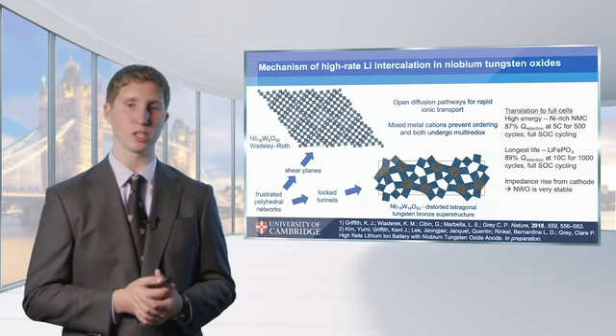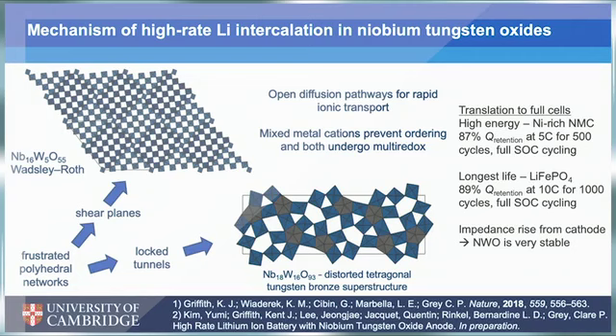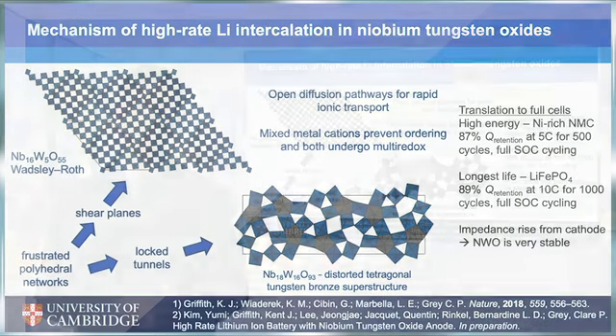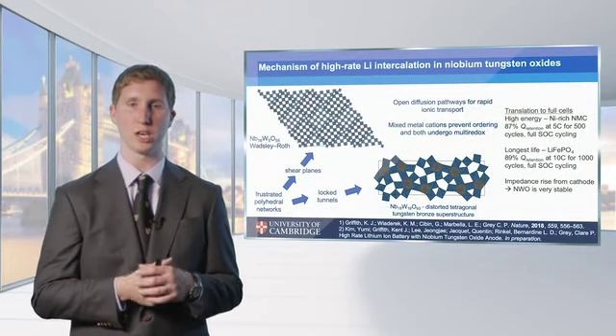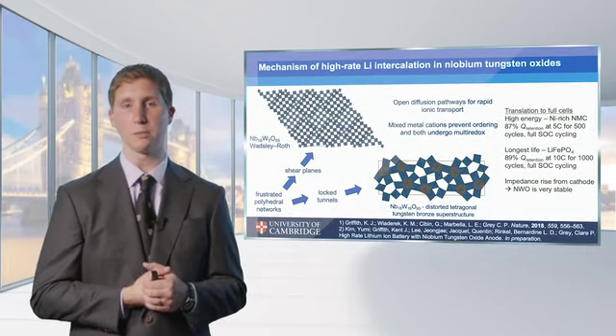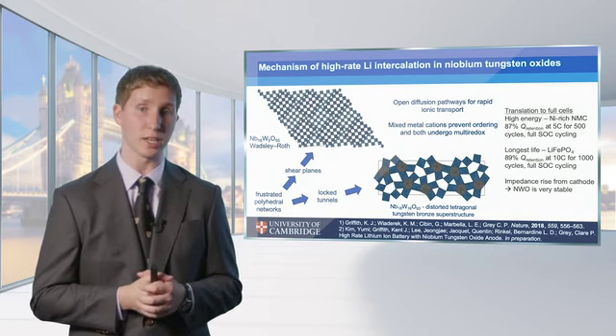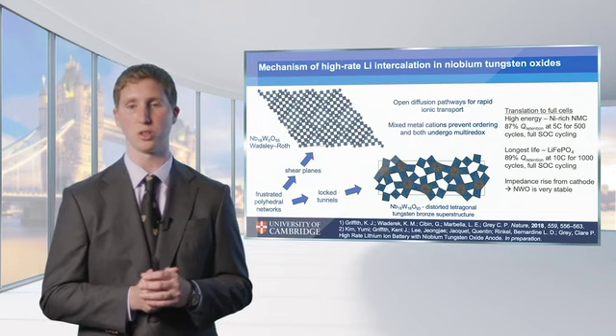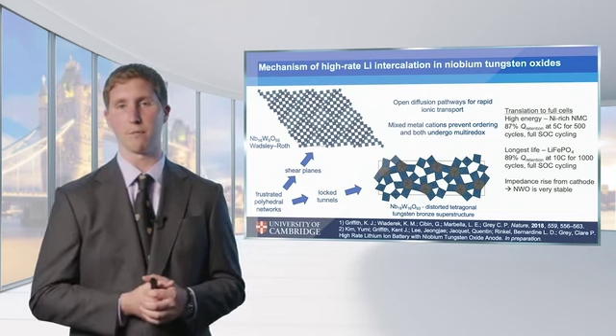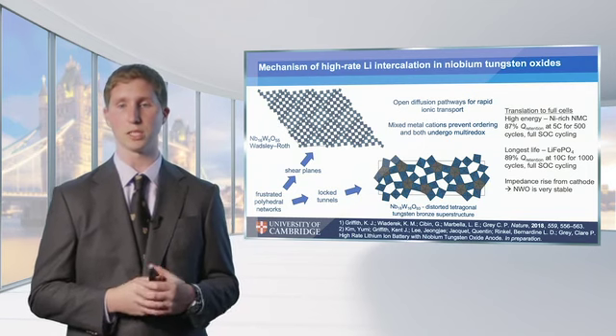And so now we're taking that further and translating this into full cells. For high energy density full cells, we would pair it with a nickel-rich NMC cathode. And for the optimal lifetime and perhaps rate, we would pair it with a lithium iron phosphate cathode. And so in our initial studies of these using thicker electrodes and full cell studies, we're able to see that we can get close to 90% capacity retention for about 10-minute charge-discharge and 500 cycles with the high energy density cells. And we're at about 90% capacity retention, even over 1,000 cycles and 6-minute full state of charge-discharge with the lithium iron phosphate.